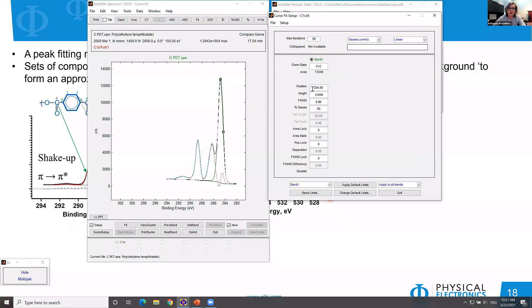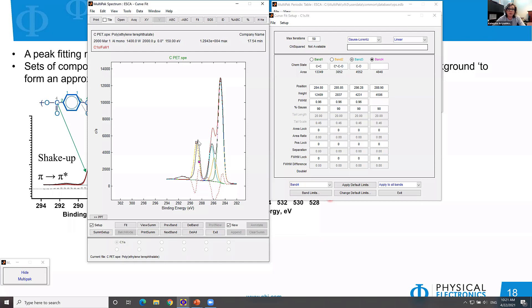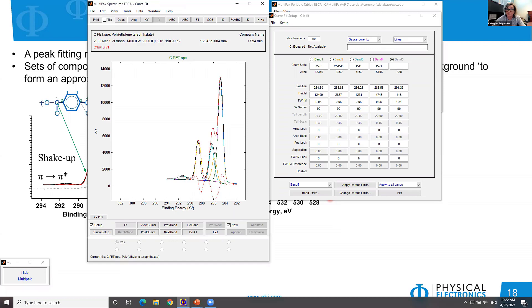The main peak is due to the aromatic structure. The second peak is for carbons bonded to carbon bonded to oxygen (secondary carbons). The third peak is carbon single-bonded to oxygen. The fourth peak is our carboxyl (C=O). And we have a shake-up due to π→π* transition — we do not ignore that; it is part of our model.